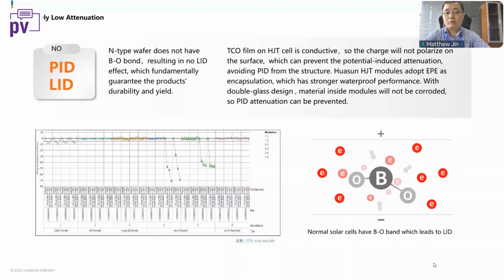It has extremely low attenuation. For the N-type wafer, there's no BO bond, resulting in no LID effect. And the TCO film on the HJT is conductive, so the charge will not polarize on the surface, which can prevent the potential induced attenuation, avoiding PID from the structure. We also use the EPE as the film, which has a stronger waterproof performance, and plus the double glass design, the PID attenuation can be prevented.